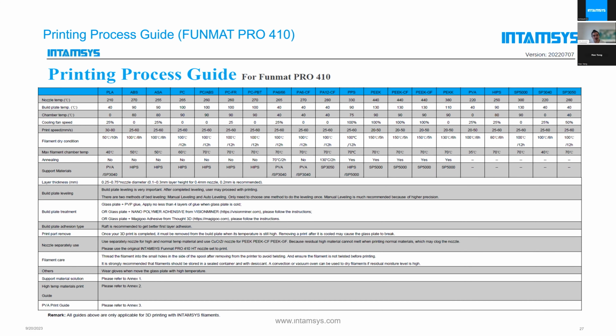And the second question of yours was how to keep a material dry. I think the best way is actually the Intam box that we now started to deliver with the 310. We use in our workshop already a couple of them. And if we have a material combination that we don't use at the moment, we place it in the box. And once we need it, we dry it again. Then we print again with it. So even if you store it dry, redrying is required in most cases. It depends a little bit on the time, but for a material like Ultem, even in a dry condition, there is a risk that it somewhere starts to absorb moisture, because also the box cannot maintain a moisture for years. It's more for like days to weeks.